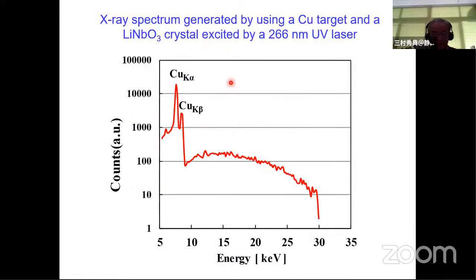This slide shows the X-ray spectrum generated by using the copper target and a lithium niobate crystal excited by the 266 nanometer UV light. The energy spectrum shows K alpha and K beta characteristic X-ray peaks attributed to the copper target, and bremsstrahlung X-rays. Bremsstrahlung X-rays were observed at higher energies up to 30 kiloelectron volts. This indicates the electrons emitted from the lithium niobate crystal. Electrons bombard the copper target during the laser irradiation, and the X-rays are generated from the copper target.